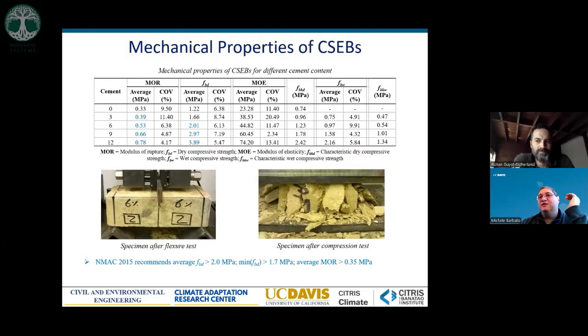And so we needed a minimum strength under dry conditions of 2 megapascal. You can see how the specimen breaks after the compression strength test on the right figure in this slide. And then we needed a 0.35 megapascal modulus of rupture, which is obtained through the flexure test that is shown on the left side of this figure. So in order to reach these requirements, we needed at least a 6% addition of cement.